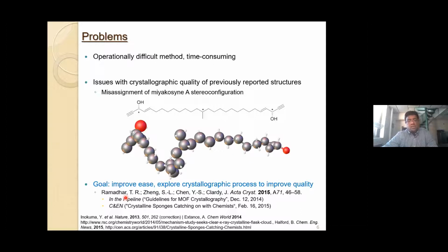And it's also time consuming to perform too. So it takes 2 weeks to synthesize the crystals, 2 to 3 days to do the guest inclusion, 2 to 3 days to do the crystallography, and a few days to do the refinement. And it might take 3 weeks or so to realize that you weren't able to get your compound inside of the crystalline sponge.